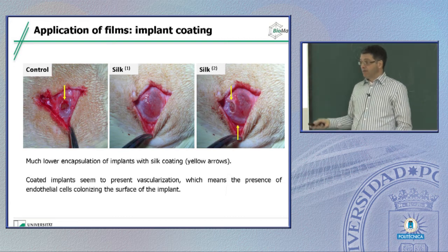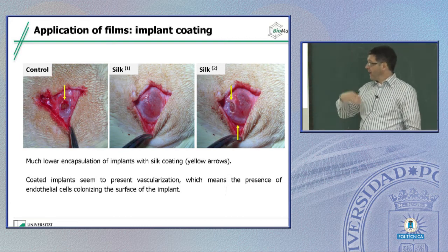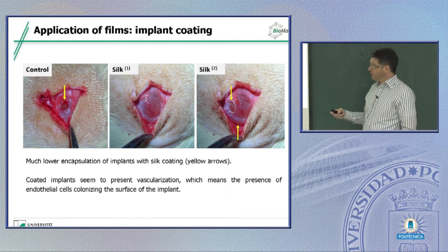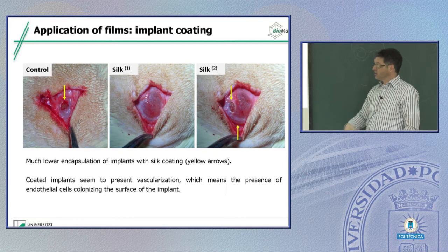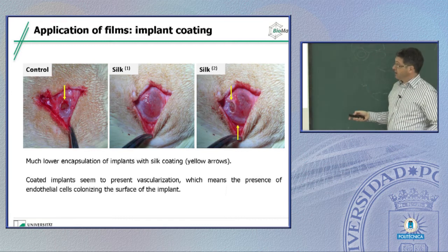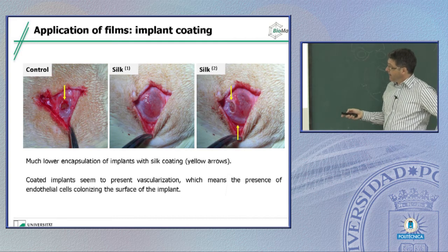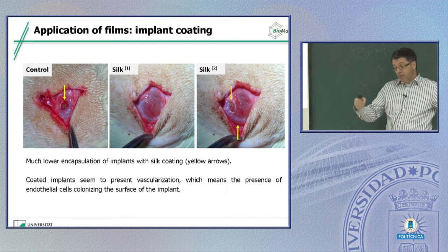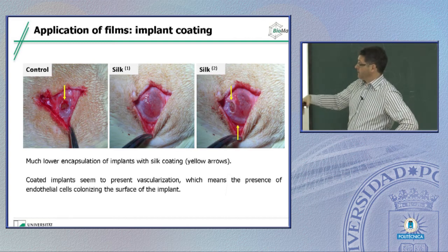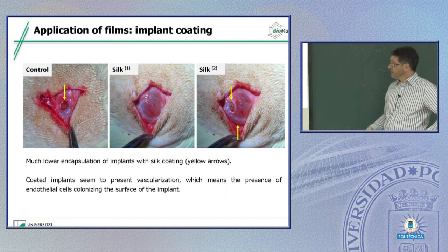And what we did, we implanted it into rats, and then of course we checked all the parameters of the rats over time, take their blood and measure if there's an immune response, and we saw no immune response, no toxicity, no other kind of irritation. And then of course we started to see what happens after 3 months, after 6 months, after 9 months, after 12 months, and we did quite a lot of animals, and there was a very intriguing finding.